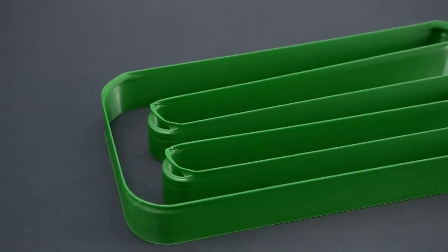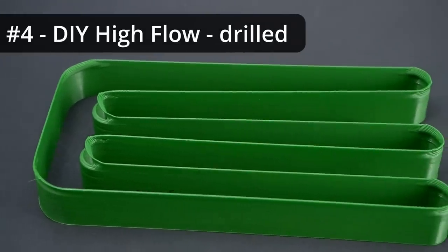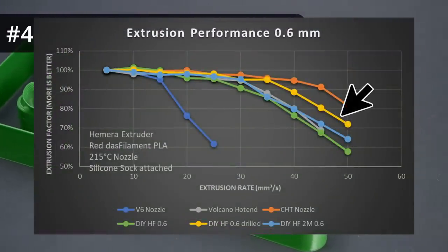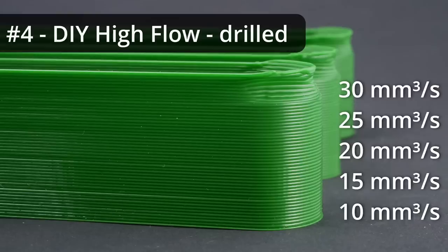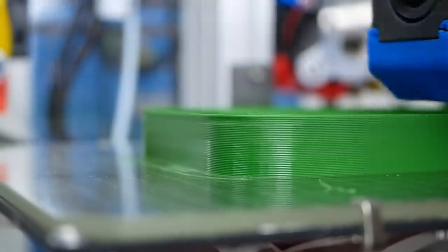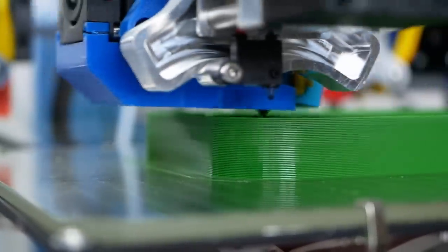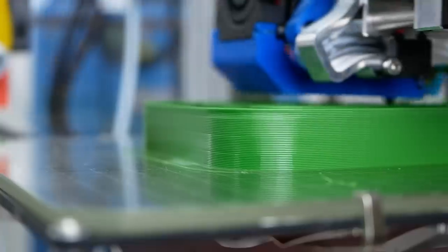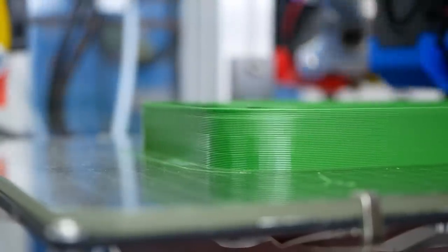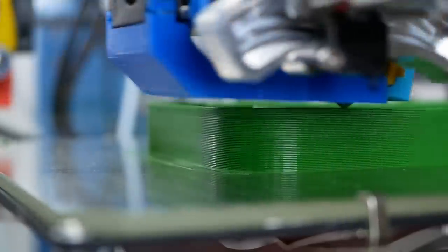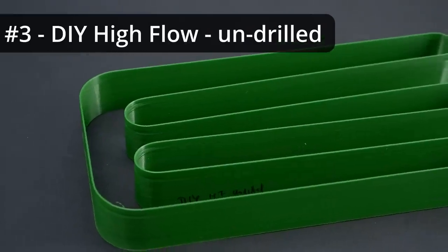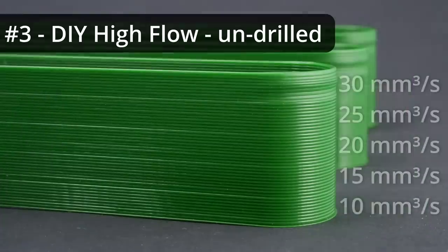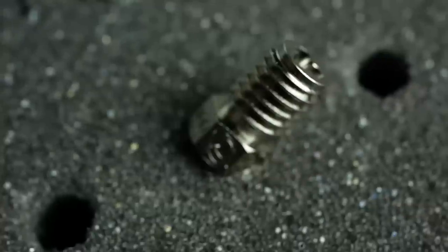Interestingly, the next contestant is my DIY high-flow nozzle that was drilled bigger and landed in second place in the extrusion test. This probably means that enlarging the hole decreased flow resistance, but somehow also decreased the melting performance because the distance from the side walls to the center of the material increased. Extrusion performance is a well-tuned system of flow resistance and melting performance. Both impact the amount of material you can push through a nozzle, but that doesn't mean that the extruded material ends up with the same properties. In third place comes my first DIY high-flow nozzle that performed well all the way to 25 mm³ a second and only then showed some degeneration.